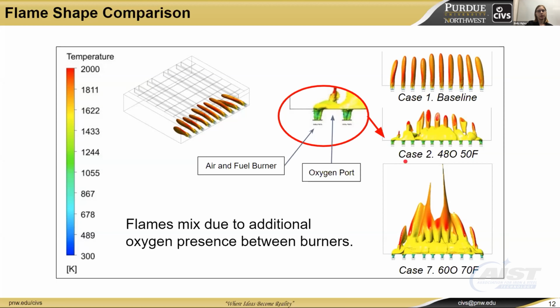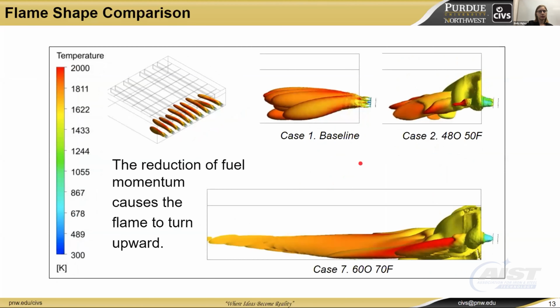Another thing to note, and this is more evident in the low enrichment case, is that the flamelet shapes characteristic of the baseline do again occur further into the furnace. However, they actually occur in line with the oxygen ports rather than the burners, and this is due to the high oxygen velocity. One more thing we can note about that mixed bank occurring near the burner wall is visible here from the side view, and that is that that flame shape actually spreads upward rather than simply being injected straight into the furnace like the flame shapes of the baseline, and this is due to reduced fuel momentum.